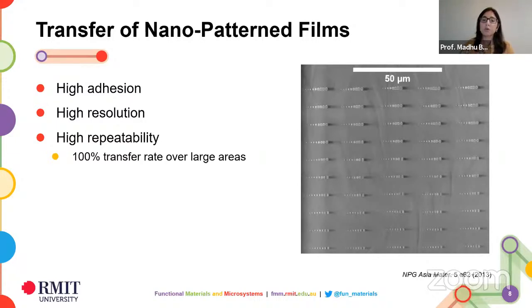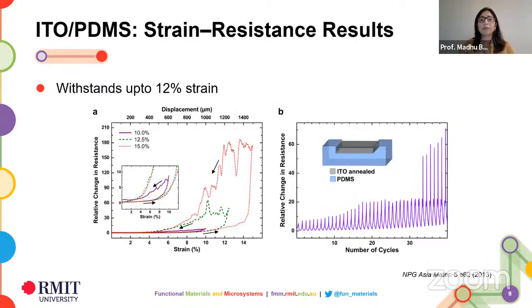And we've tried this over up to around a 4-inch diameter silicon wafer, and we get a 100% transfer rate and repeatability across the entire diameter of the silicon wafer. So you can maintain the resolution and also have high repeatability. So we were quite happy with the results. We thought, okay, we managed to get an oxide layer which has been transferred onto silicone.